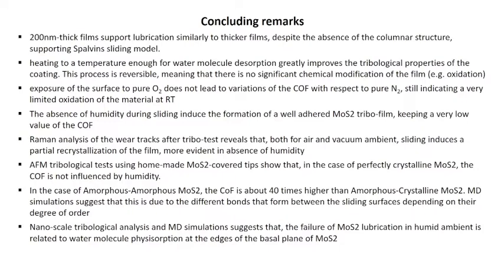Heating to a temperature slightly enough to induce the water desorption, you can have very good tribological performances even in presence of humidity. And this suggests that oxidation is not the main origin of MoS2 failure. This has been proved also measuring the coefficient of friction in a saturation of oxygen, which shows that even if oxygen is always present in the ambient, we do not get the worst tribological performances of MoS2.